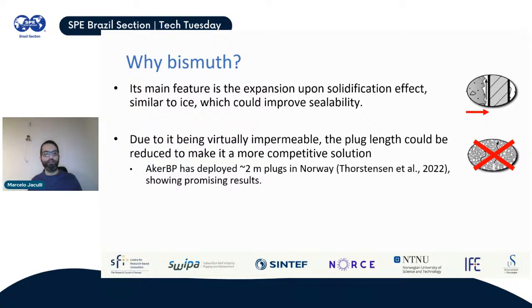And then we have an example from Aker BP that deployed some 2 meters plug in Norway. And it's on this reference that I can, if anyone is interested, can contact me. And they showed some promising results. But it was an initial test. The plug that they built was an environmental barrier, so it was at the very top of the well, not very deep downhole as the last plug that you have there. But in any case, they also had to keep the cement plug as well, because you still cannot deploy only a bismuth-based solution. You have to deploy the cement and the bismuth-based solution. But they were able to verify some good results on this.